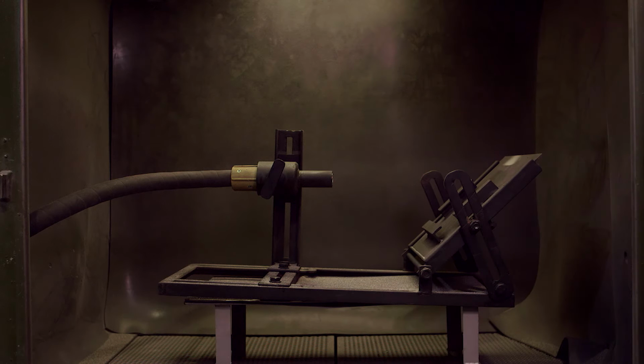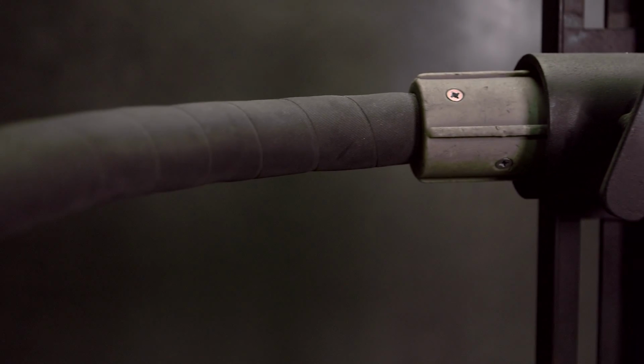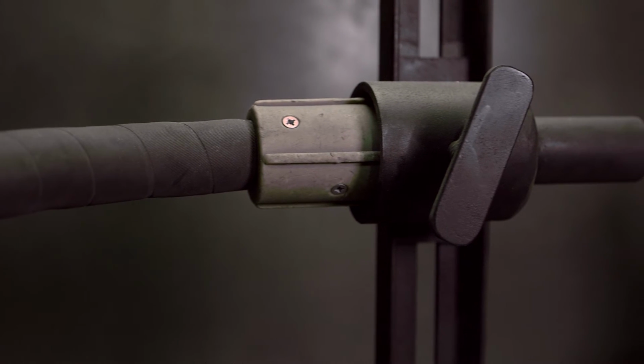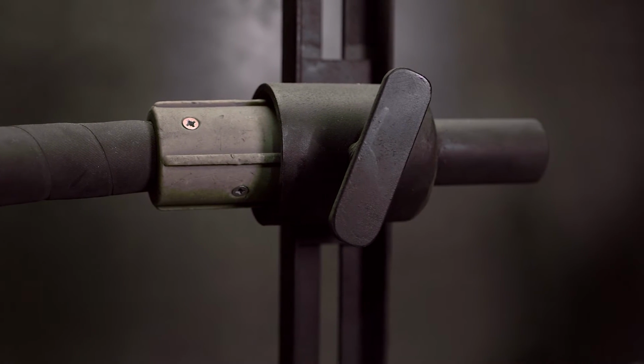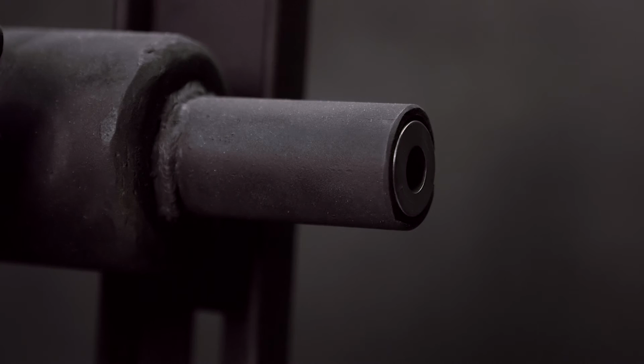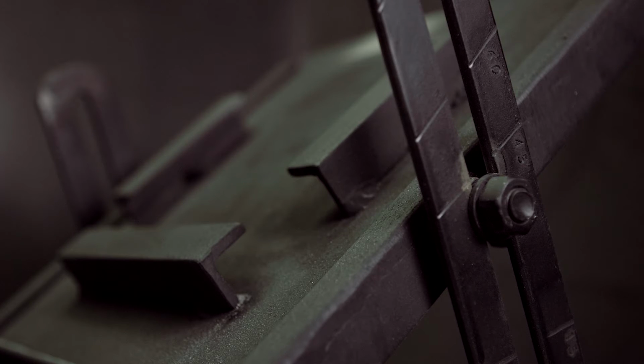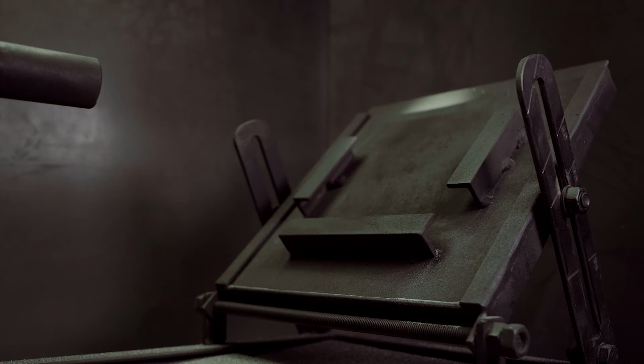The in-house tester is a free particle jet abrader. The device consists of a compressed air supply, abrasive media, a pressure pot, hose and nozzle. It is a version of grit blasting with a fixed size nozzle, angle of nozzle to the test piece, usually 45 degrees, and distance from the test piece. It has a constant air supply volume, pressure and abrasive flow.